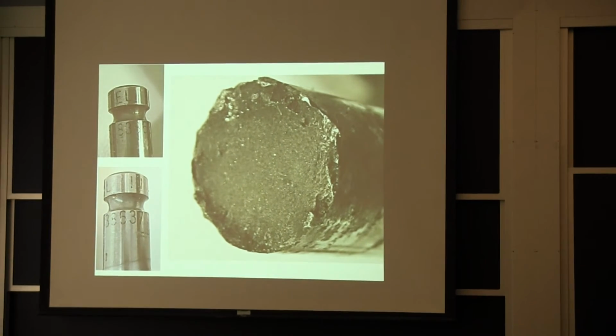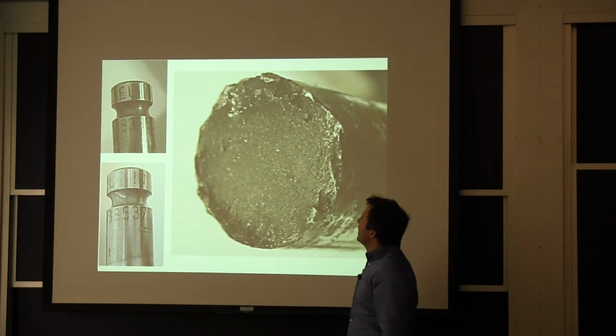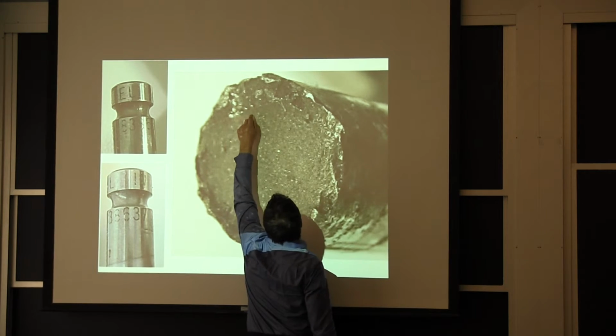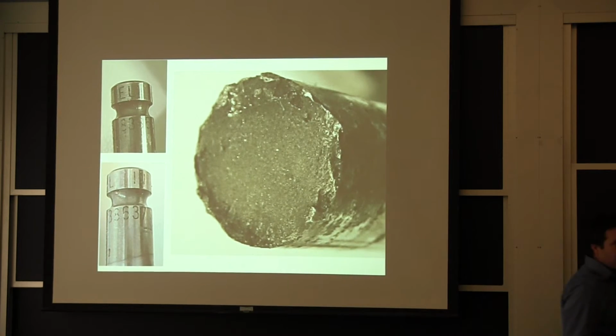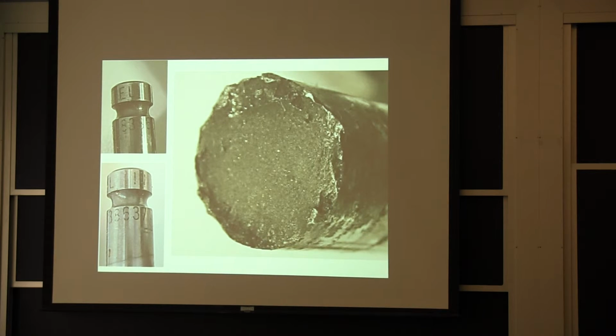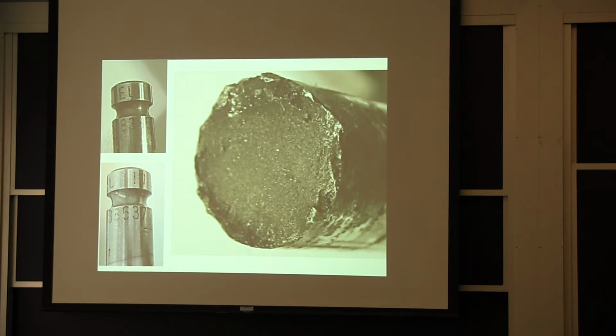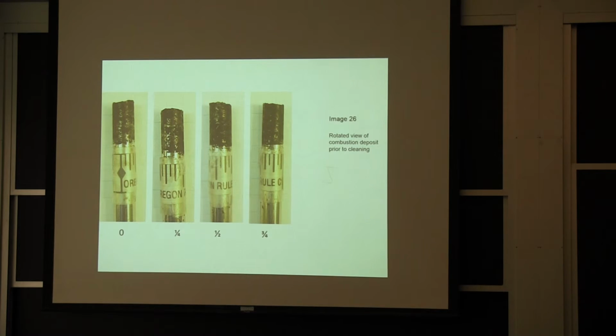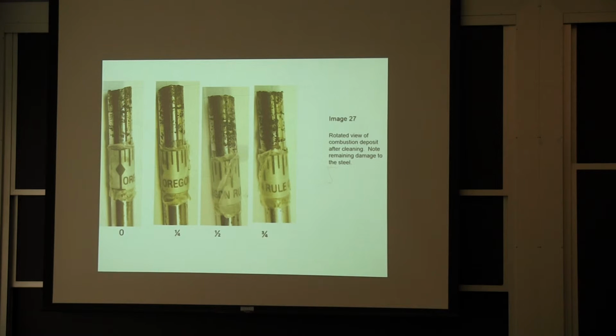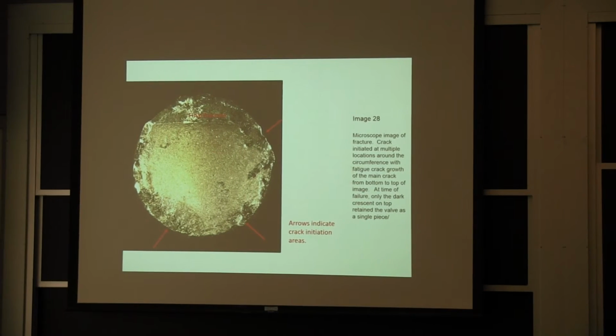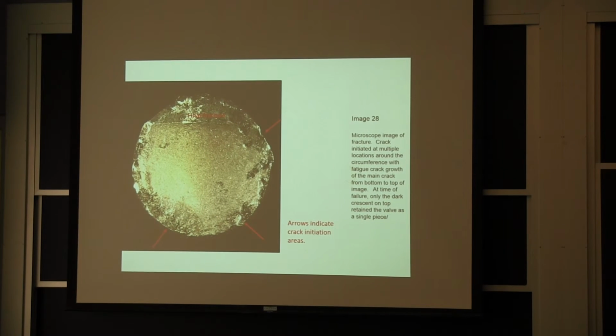It was dirty. When I'm looking at this, I was thinking already, oh, maybe this is my final crack propagation line, and what is on top is the final fracture, but I couldn't say for sure. So when I was talking about documentation, one of the first things I said was, I need to image this before I clean it up. This was the condition of the deposits, then I put it in an ultrasonic bath with some mild detergent, and I got to this point. It's still not exactly clean, but at least I was able to look at the fracture surface and make my interpretation.